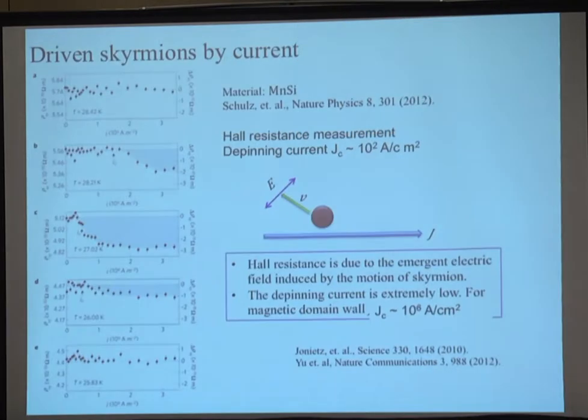So how do you tell your skyrmions are moving? Well, you can directly visualize them with Lorentz microscopy, or with neutron scattering. But the other way is with transport, by looking at changes in the topological Hall effect. We've previously done a lot of work in superconducting systems, where again you can apply a current to your vortices, in that case with pinning.